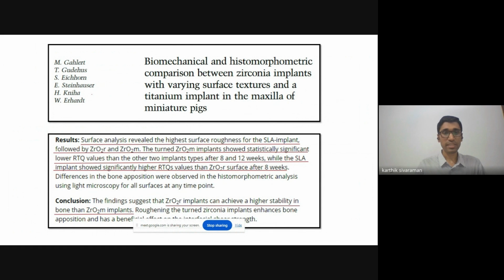Now, much later, we see Gahlert et al. conducting a study in around 2007, in which biomechanical and histomorphometric comparisons were performed between zirconia implants with varying surface textures and a titanium implant in the maxilla of a miniature pig. So basically, a titanium SLA surface implant was taken, and it was compared to 2 zirconia implant specimens. One set of zirconia implants had a machined smooth surface, and the other set was made rough by sandblasting.